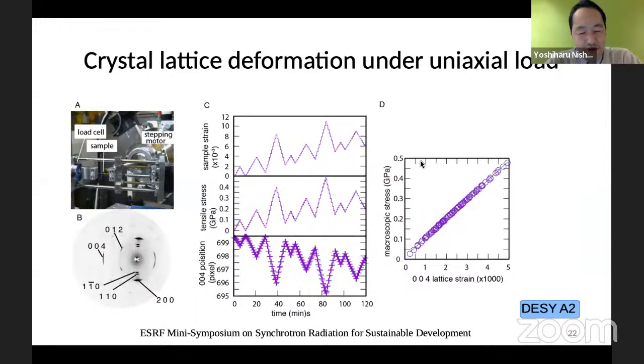So here we wanted to look at the basis of these mechanical properties, and we are looking at the lattice deformation under different loading. In this case, we again prepare uniaxially oriented samples, and we stretch along one direction and see how the lattice is moving, so how the crystal is responding to the uniaxial load. We have distinct peaks appearing on the pattern, and we follow the displacement of each of the peaks. We have the macroscopic stress or load we applied on the sample, and then we can see the lattice strain that follows a straight line that gives us an idea of the elastic modulus along the fiber direction.